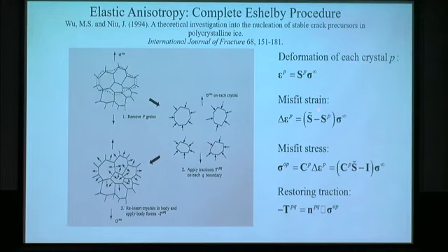But overall, as a polycrystal, the strain is S tilde times sigma infinity. That is the polycrystal strain. S tilde is basically the average elastic compliance of the polycrystal. So if you take away S^P sigma from the average strain of the polycrystal, you get a misfit strain. So each of these, subject to epsilon P, could not be put back into the polycrystal because they have some misfit.